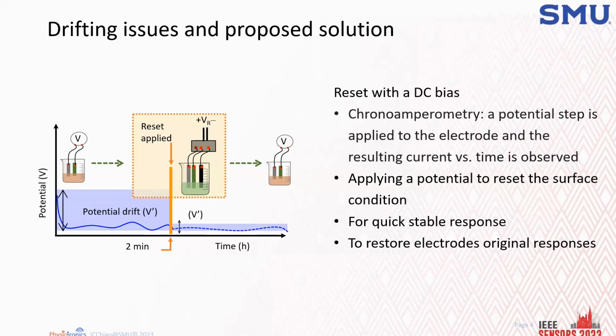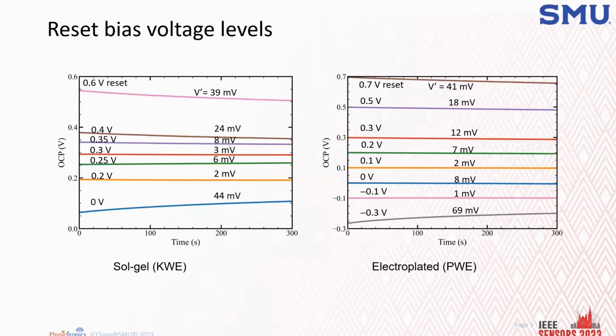So what we did is use something called chronoamperometry. In that technique, you apply a potential voltage and you observe the current change with time. We found that the current can settle very quickly. So we are thinking, can we apply a DC bias to the sensor to modify the oxide surface in order to make the surface like the original one? Then I can take the data every time as if this is a fresh sensor. So we want to use this to quickly settle the potential so we can get a better response time.